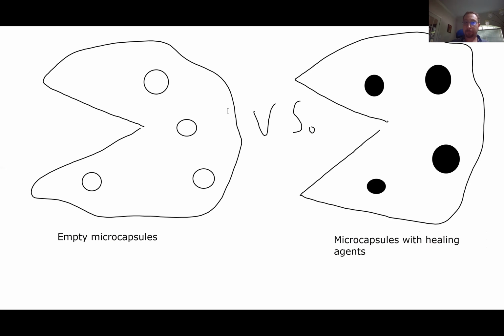In place of these empty microcapsules, it was solid material that is now taken away. So because of these two mechanisms, either crack tip blunting or removal of the material, the fracture toughness of a material with empty microcapsules will also depend on microcapsule concentration.